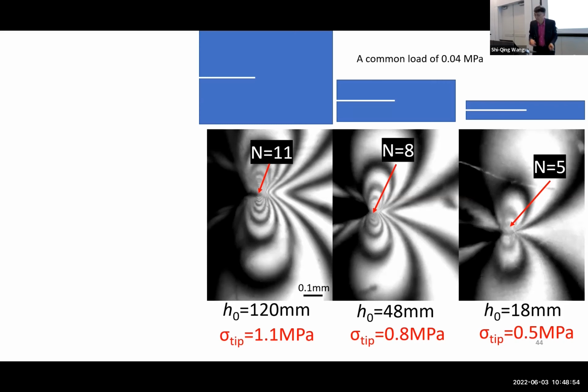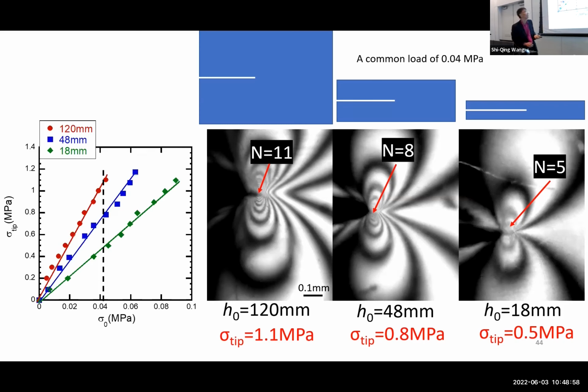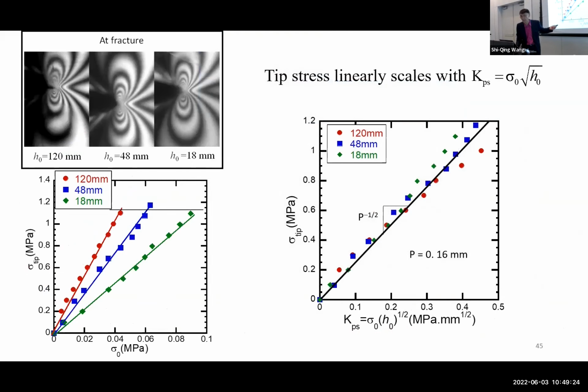Of course, then it breaks early. Maybe it takes more than a minute for you to absorb, but that's what happens. So this is a different H. At the same load, the taller one has much more stress at the tip than the shorter one. So it turns out this H magically comes into the tip stress such that this product has no H dependence anymore for the GC. I know I'm running a little fast, but believe me, the end story is this load parameter becomes a function of the height, because that's the only length scale left. The cut is so large, the width is so large, the only length scale is the height. So in fact, it's inescapable. It's a cheap solution story because you're missing a length scale. So it's quite trivial in that sense.